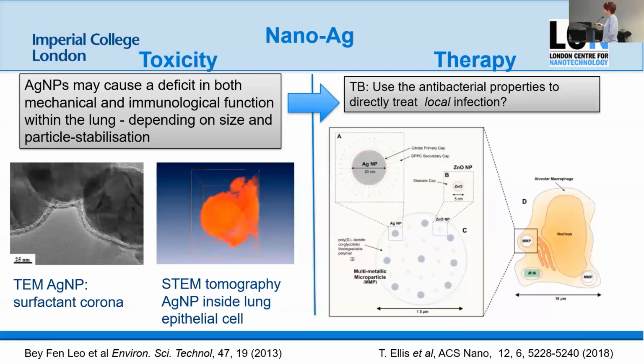This is an electron tomography image of a silver nanoparticle. It's actually inside a lung epithelial cell. So this was from a tissue culture. We've blanked out, so you can just see the particle. And what you can see is this very dense core, which let me show you. And then this diffuse layer of stuff around the outside. And that's the nanoparticle dissolving, so it's releasing some silver ions. But it doesn't get very far because it reacts very rapidly with any spare sulfur that's around.